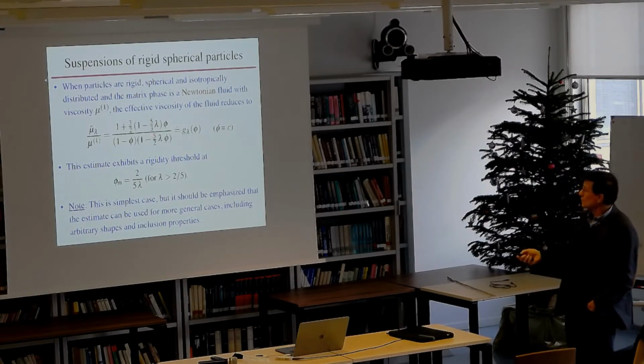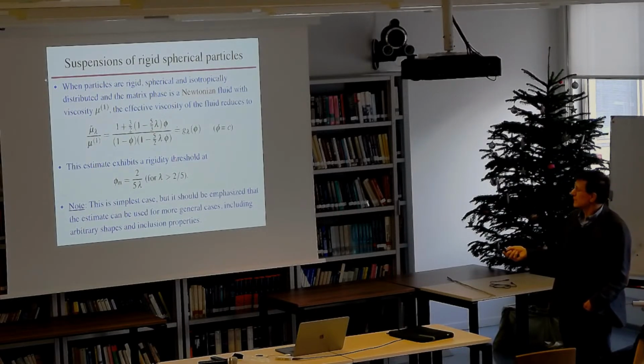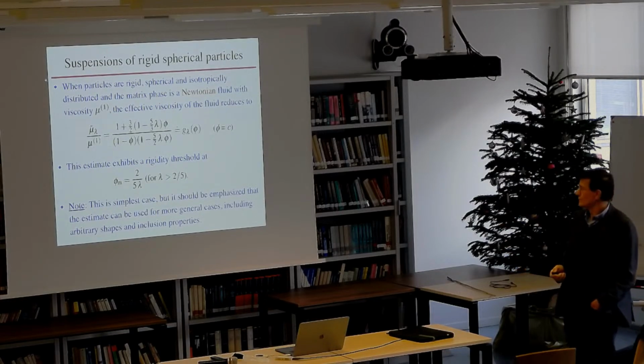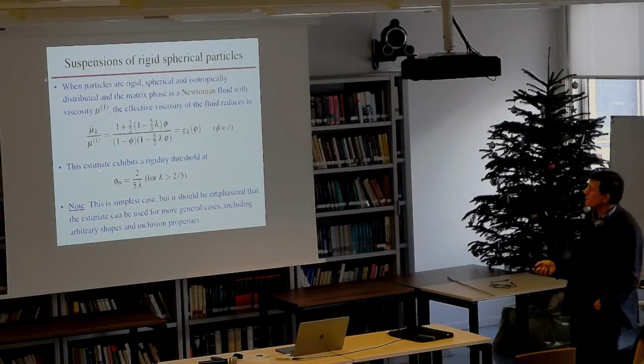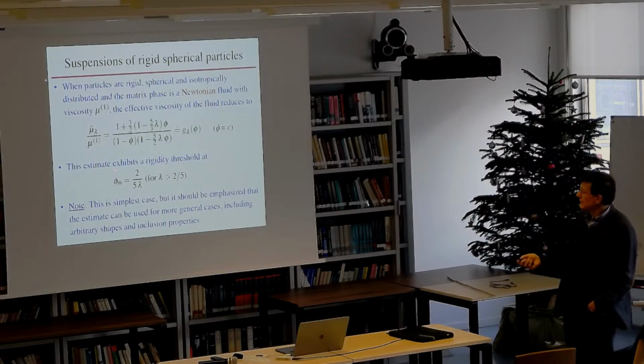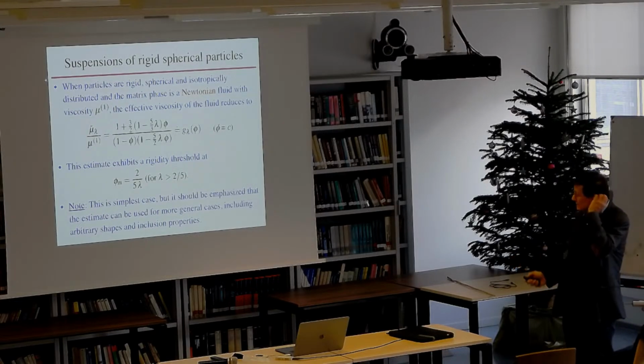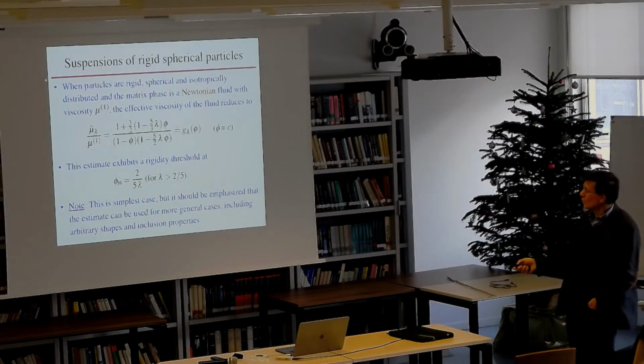So when lambda is equal to 0, this is the Hashin-Shtrikman bound. When lambda is equal to 1, this gives you the self-consistent estimate for this particular type of microstructure. In between, you get something that is in between the two results, and that means that now we have a rigidity threshold. This thing blows up when phi reaches this value that depends on lambda. So you see when lambda is equal to 1, this gives you 40%, which is the self-consistent estimate.